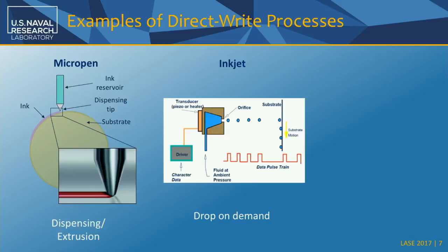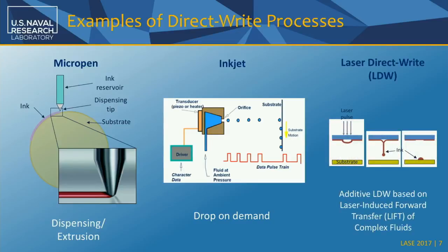electronics. For example, inkjetting has been used to print electrodes for photovoltaics, for large-scale photovoltaics, solar cells. But the key here is that with both of these techniques, you have to be careful about the material that you put on the nozzle or on the dispensing head, because you can clog it, you can block it, and you also have to worry about the nature of that fluid, if it's the right viscosity for inkjetting or for micropen. When we use the Laser Forward Transfer technique, the laser Direct Write technique that I referred to, the nature of the material is not that critical.